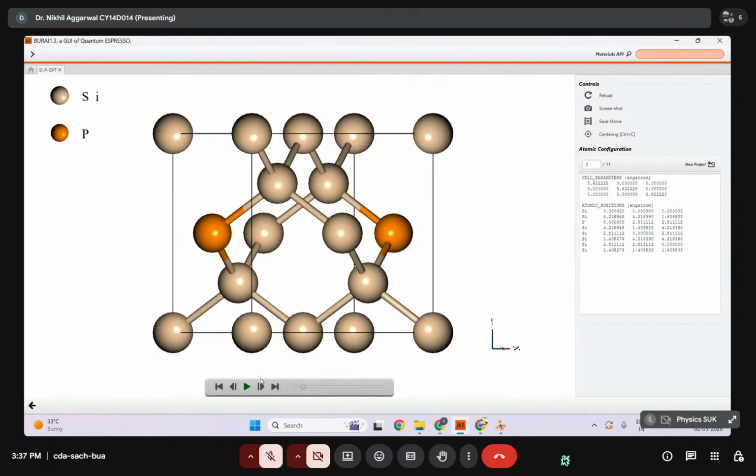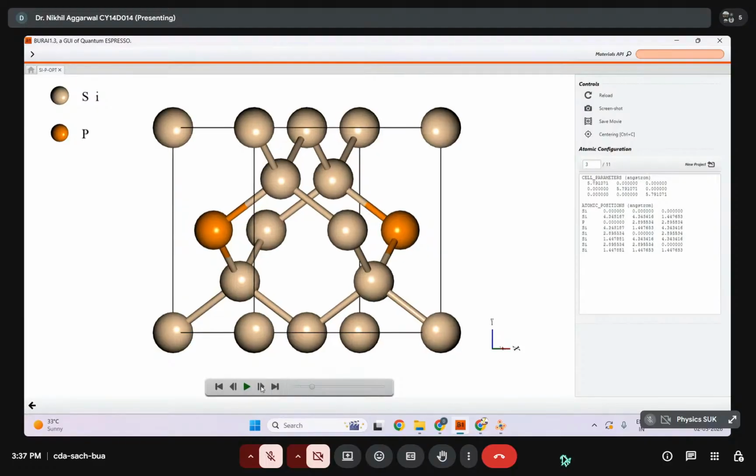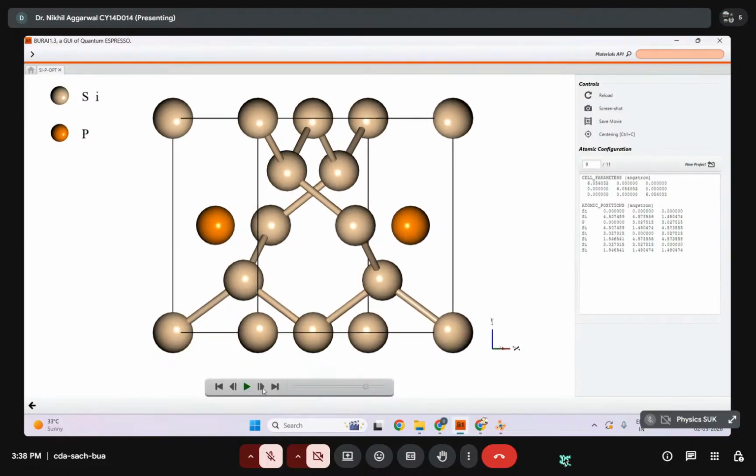And that is why it again did the residual force calculation, force being a vector quantity, it changed the atomic position in that direction and found the next structure, structure number 3. Again, it found the residual force is greater than 0.001 and successively, to minimize the residual force, it ended up at the 11th structure wherein the residual force is less than 0.001 eV per angstrom. Now, this structure you have to take for all subsequent studies, whether the SCF convergence to estimate the cutoff value, the band gap, magnetic study, or whatsoever.